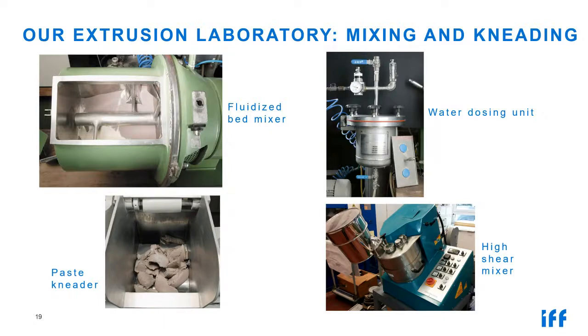Left above, a fluidized bed mixer, which we are using for the dry mix. This is the only way to get a homogeneous dry mix between heavy powders, heavy particles like silicon carbide, or even, there are many others, zirconia, for instance, and light particles, for instance, cellulose ether. Yeah, if you have a slowly running mixer, you never will get a homogeneous distribution, and this is, by the way, one of the reasons for a later crack formation.